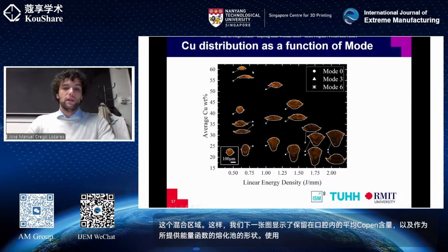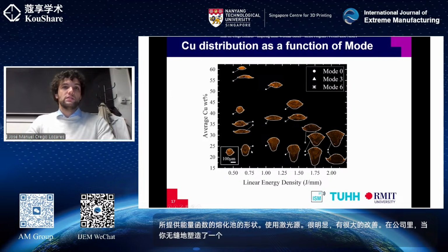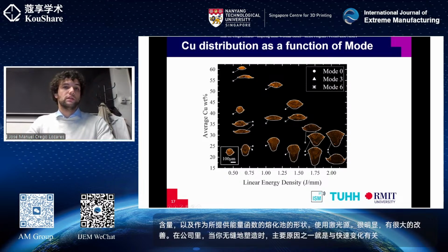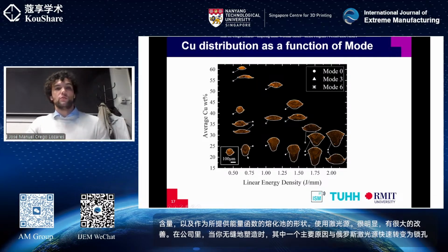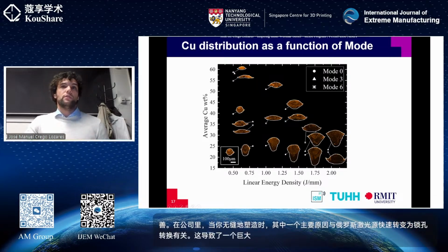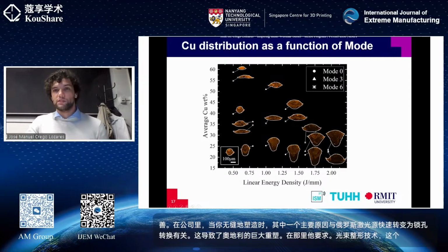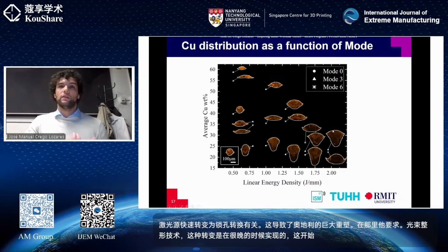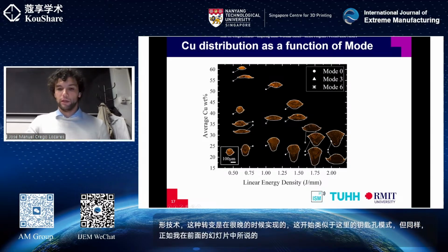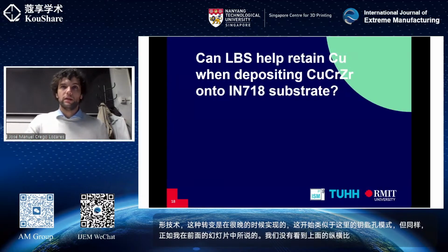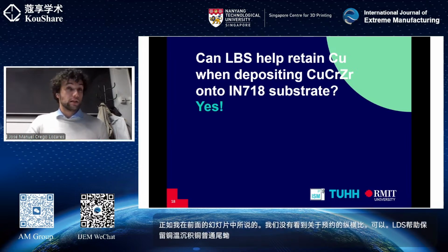It was clear to see that there was a great improvement in the copper retention when using laser beam shaping. One of the main reasons is associated with the rapid change to keyhole transition by the Gaussian laser source, which leads to a huge remelting of the substrate. Whereas for the laser beam shaping technologies, this transition is achieved much later, which starts to resemble keyhole mode here. But again, as I said in the previous slides, we didn't see an aspect ratio above 0.8. So can LBS help retain copper when depositing copper chromium zirconium onto Inconel 718 substrate? Well, the answer is yes, it can.